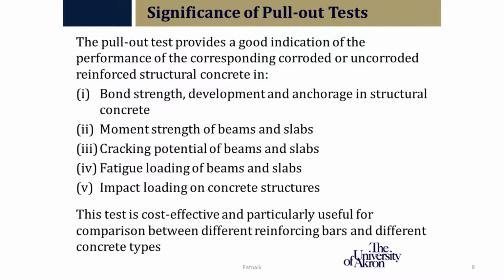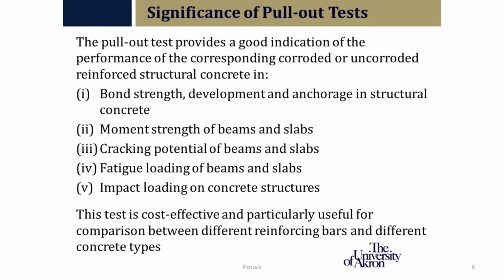So the pull-out tests provide a good indication of the performance of the corresponding corroded or uncorroded reinforcing in structural concrete: bond strength, development and anchorage in structural concrete, moment strength of the beams and slabs, cracking potential of beams and slabs, fatigue loading of the beams and slabs, and impact loading on the concrete structures. So they're trying to simulate an environment in which, this is what it is in the real world. So they're cost-effective tests, and they certainly have done these over time.